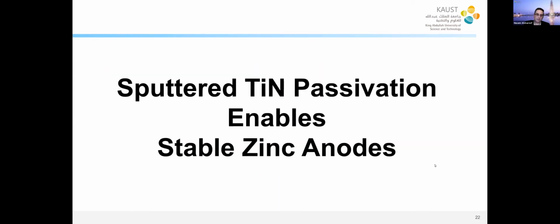The second example, I want to go to the anode now. What problems do we have at the anode? I explained earlier, we have zinc dendrite. We have corrosion of the zinc. We can also have hydrogen evolution and so forth. So one of the strategies is surface passivation with polymers, surface passivation by alloying, surface passivation by different techniques. In this case, we used a sputtered titanium nitride layer. Titanium nitride is metallic, it's conductive, so we thought it would not degrade the overall conductivity of the anode. So let me tell you about the results of this experiment and how successful it was.